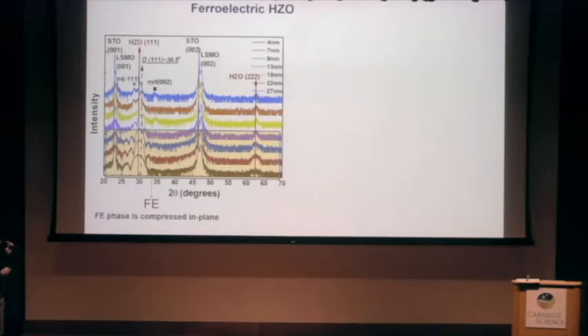And so to understand that, we did structural characterization using both XRD as well as electron microscopy. So here I show theta-2theta XRD plots as a function of the film thickness. This is a busy graph, but I want you to note a couple of things. One is the literature value of the orthorhombic 111 is here. Whereas what we see in films which are boxed here, they are the ferroelectric films. The rest of them are not ferroelectric. So beyond this thickness, it is not ferroelectric.